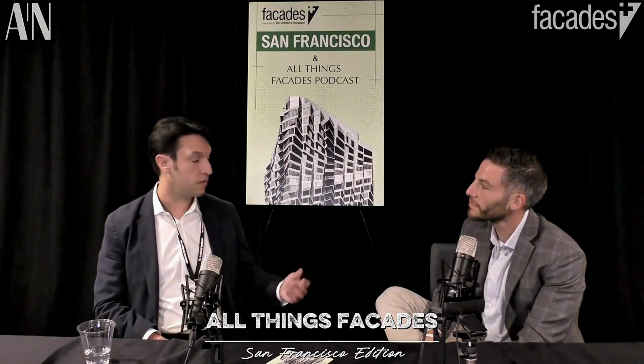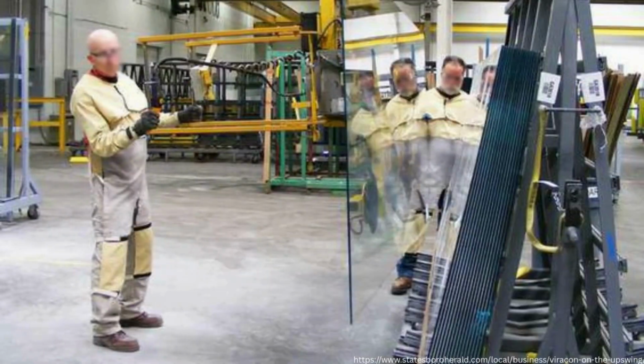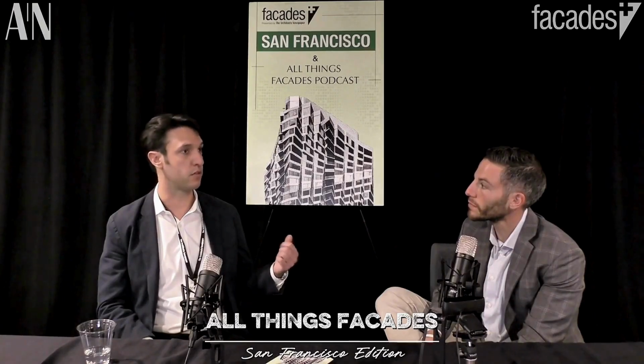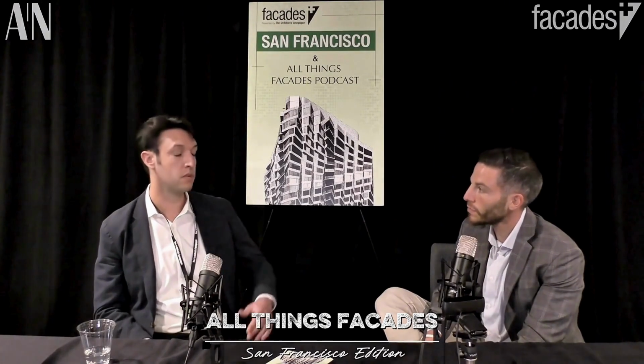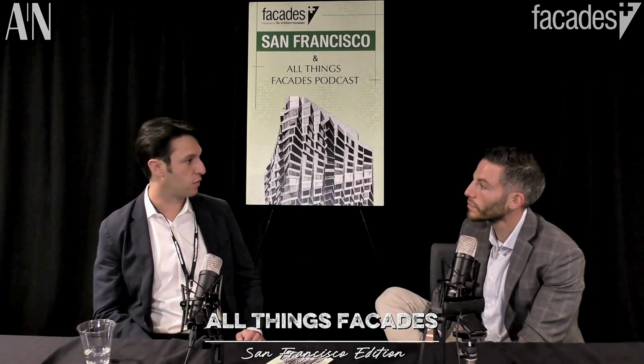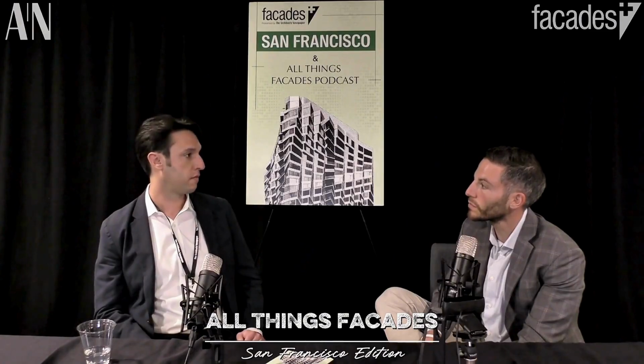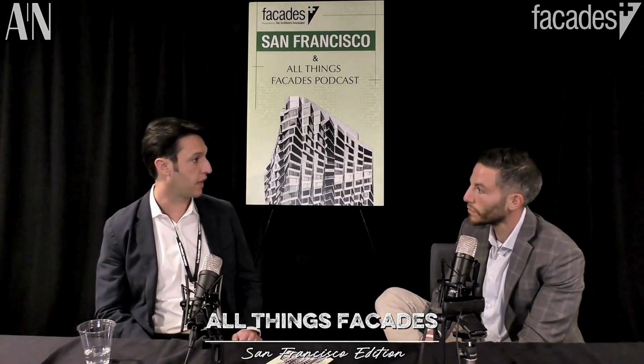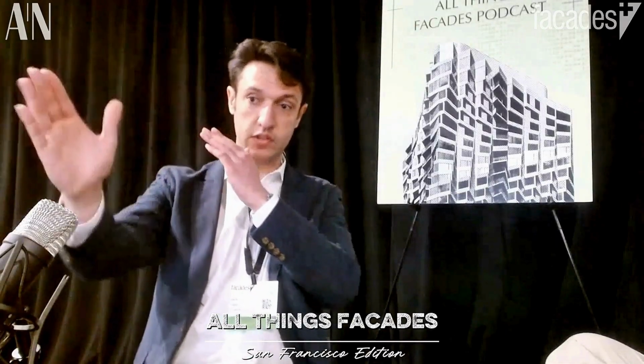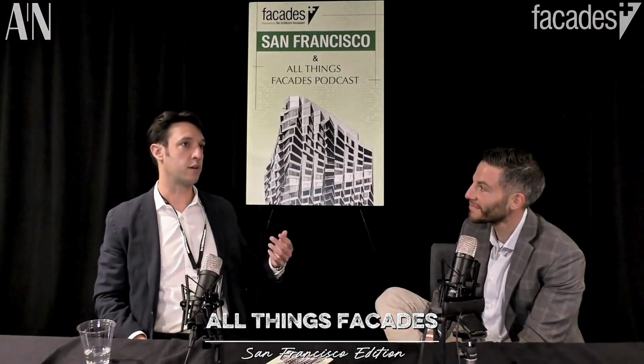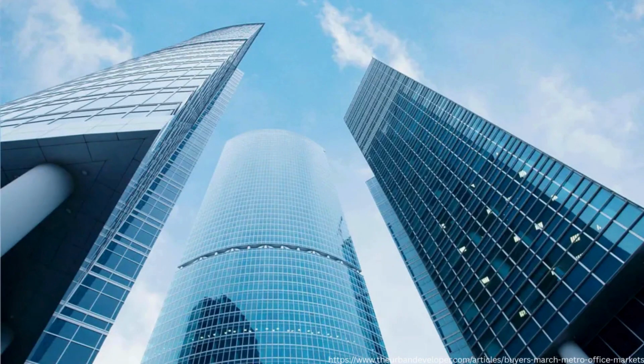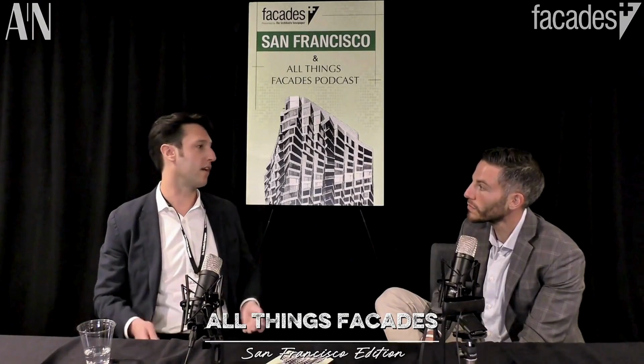On the point of innovation, Viracon has had a huge advantage with flatness because of that process, especially with thicker outboards, like 5/16, 3/8. However, for the past couple decades, we have used roller wave measurements to measure distortion, so peak to valley distortion. That's a really antiquated process. It's just a lineal measurement going down the center of the glass. So when we would talk to architects, hey, you might want to consider 5/16, 3/8, it's going to be flatter, we couldn't really quantify that.